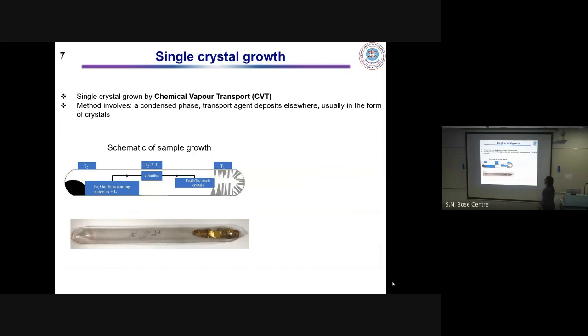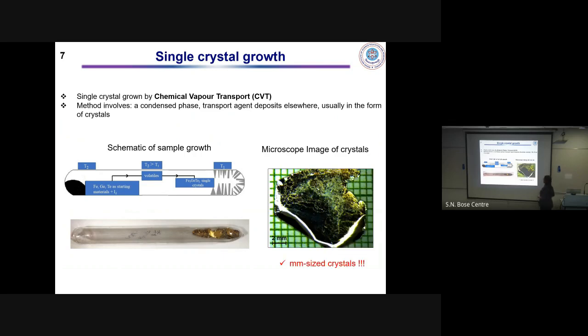So, okay. Before moving on to any transport measurements, it is very important to have good quality single crystals to perform all these measurements. So we have grown single crystals by the chemical vapor transport method. This is the schematic of the sample growth. You have the polycrystalline starting elements, and in this sample, we have used iodine as the transport agent. And to keep it in the tubular furnace, you have to look out for a proper temperature gradient, and we were successful in getting the single crystals at the cold end after about 2.5 weeks. Okay. And this is one of the images where you can see a quartz tube containing single crystals. And we were successful in growing large single crystals of Fe3GeTe2.